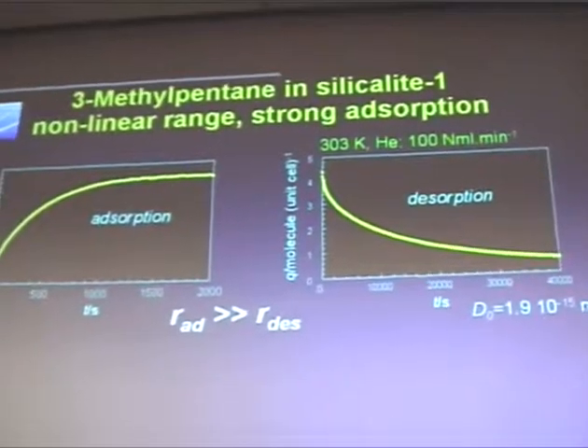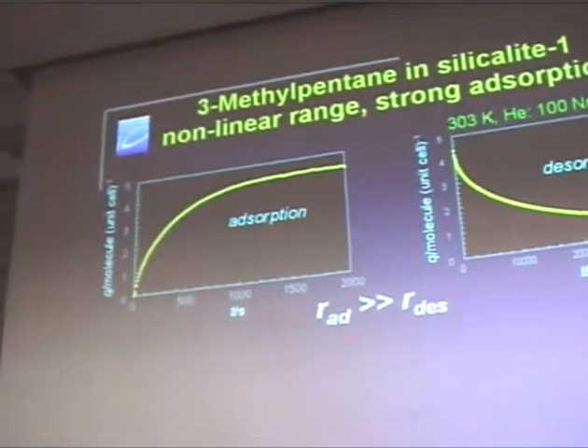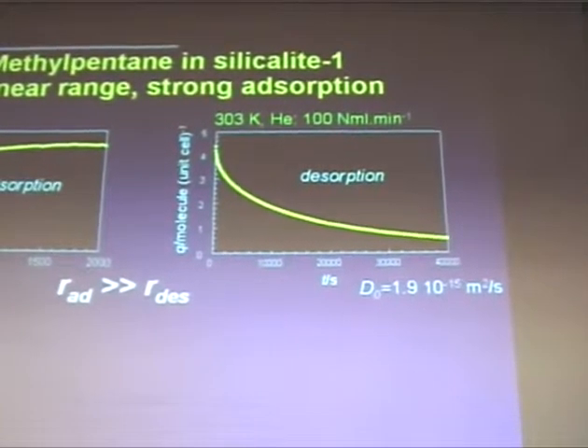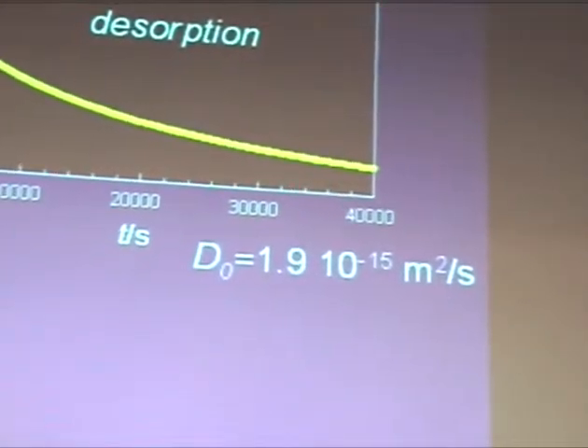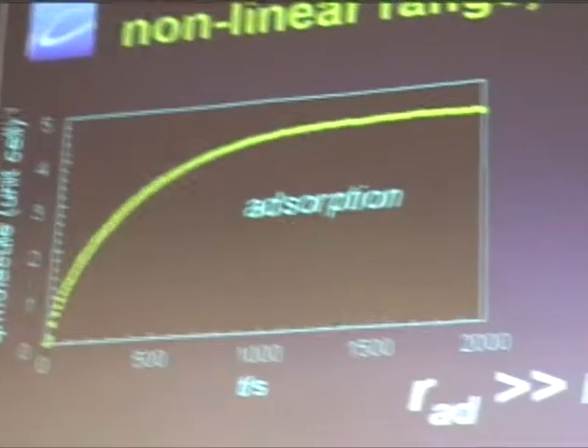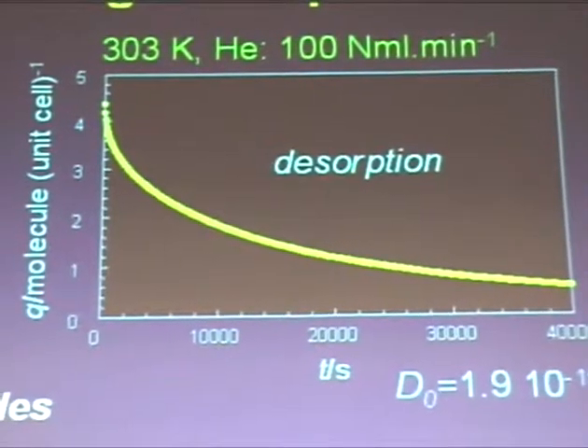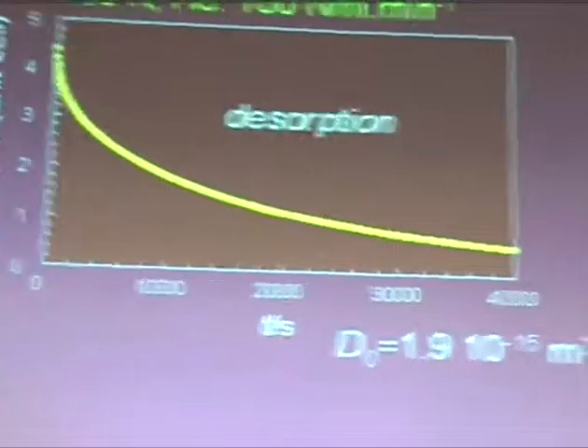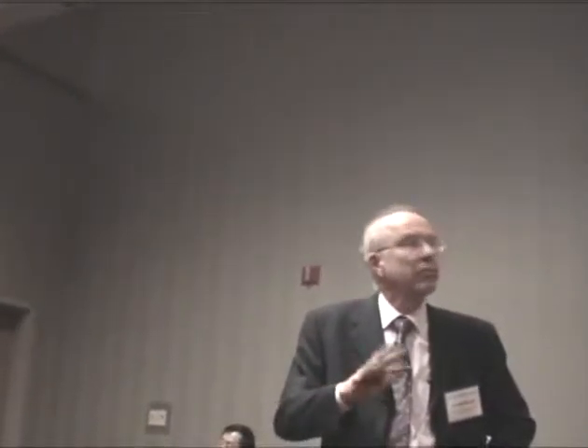That you should expect for several reasons. One, of course, is that our model predicts that, because the occupancy is in the model. In fact, Fick's law doesn't hold; you need a chemical potential-based formula that's driven. But there's another thing. Absorption is exothermal, so there's no certainty that you're not at a higher temperature than you think. In a normal microbalance, that difference will be enormous, but in the TEOM it could be too. So we concluded that you should always calculate the diffusion coefficient in the model from desorption data. And it goes with the TEOM very reliably.